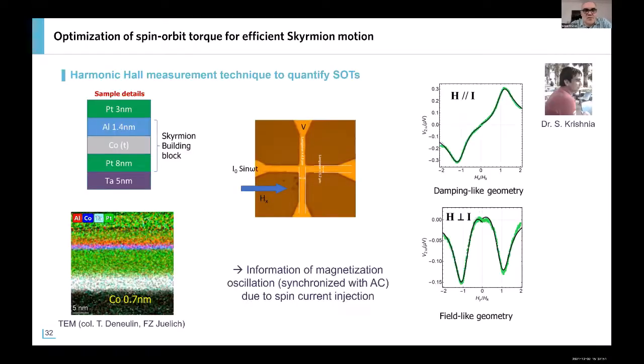So what about the optimization of the spin orbit torque for improving this motion and nucleation experiment? Here we show some very recent results done by a postdoc in our group, S. Krishnia, focusing on a quantitative determination of the spin orbit torque. This is a mechanism that is used for the motion of the skyrmion. As I said in the very first slide, spin orbit torque is related to the conversion of charge current into pure spin current. And these spin currents, once generated, can be transferred onto the local magnetization, in our case, the magnetic layer.